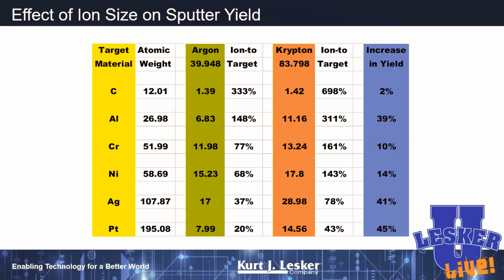Notice that for every 1 argon ion that hits chrome, we get about 12 chrome atoms out. And for platinum, we get about 8 out. So it's not necessarily a linear relationship between these masses. If we're not happy though about our deposition or our sputtering rate, we can go to a heavier ion. So we can go to krypton, which is roughly double argon, and you can see that we do see some slight increases in our sputter yields by going to a heavier ion.